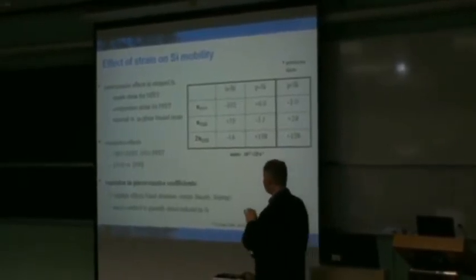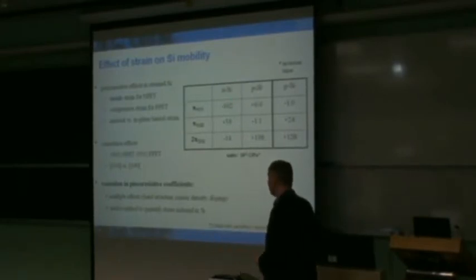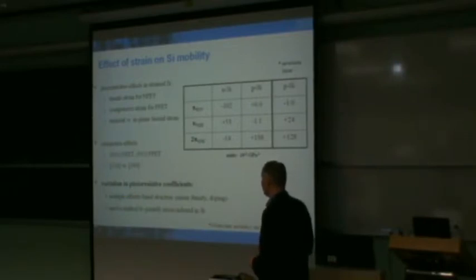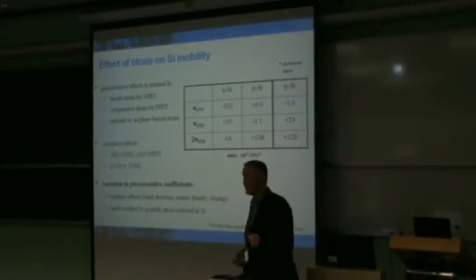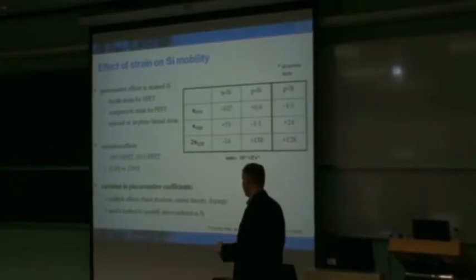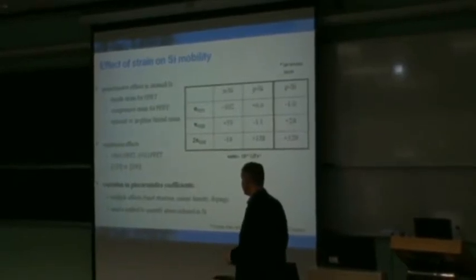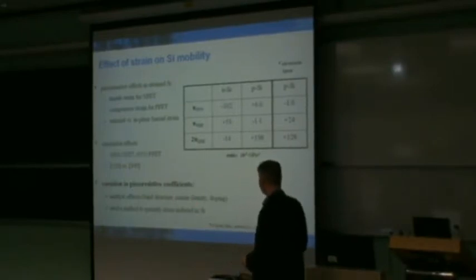So not only are there many parameters that go into this, and these numbers came from Smith's first paper, but we do know in reality there's a wide variation that can occur, and it has to do with the fact that there's a complicated band structure at play here, not just a single force or orientation of forces. So we know that the band structure and the carrier density all impact these, but also the doping. And unfortunately, this is a nonlinear effect that we see in the piezoresistivity.